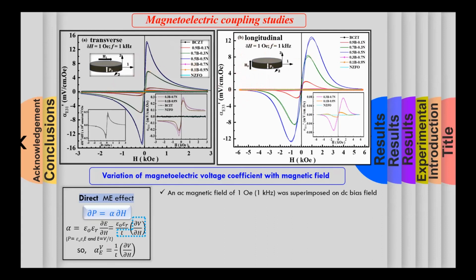In both orientations of the field, the composites show similar behavior. That is, the response increased, reached a maximum, then decreased, and then finally the values were 0. And when the field was reversed, the response becomes negative, but it traces the same field dependence as in the positive case. If we compare the two modes, of course, the behavior is the same, it increases and decreases, but there is a subtle difference between the two.